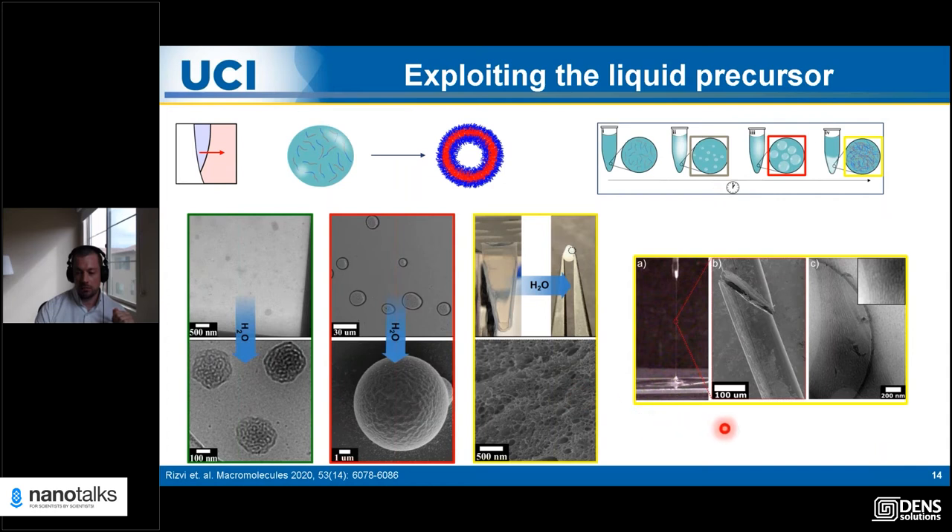The really interesting thing Arne found is that if you take out the coacervate layer after macroscopic phase separation, you can actually pull polymer fibers out of this layer. This is interesting because many living systems use coacervate precursors to make fibers — spider silk protein, for example, first undergoes liquid-liquid phase separation to form protein-rich liquid droplets, and the spider uses those droplets as a precursor to spin silk. We're showing the same physical chemistry — without proteins, we can use these liquid phase precursors to spin fibers out of something which under other circumstances would form nanoparticles, microparticles, or macroscopic systems.